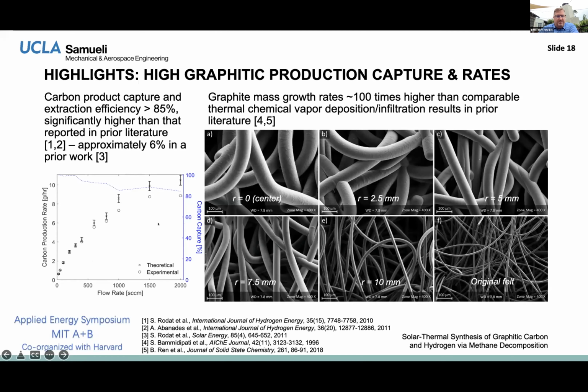We're capturing nearly all of the carbon. If we vary the flow rate through the system, and we go really slow, we're getting almost all of the input carbon in methane captured as a solid, and this is based on mass measurements. And that was also a surprise. We had very little of those problems with extraneous deposition on windows and clogging and so forth. It almost all goes onto the cloth itself.